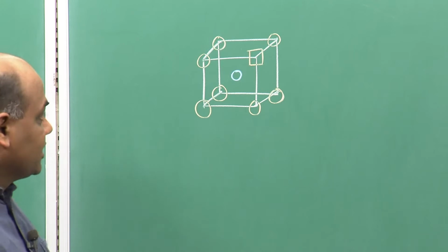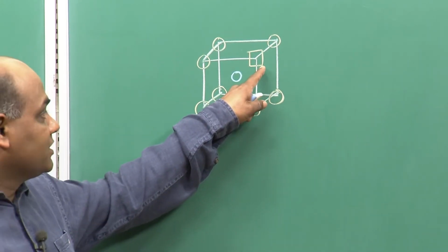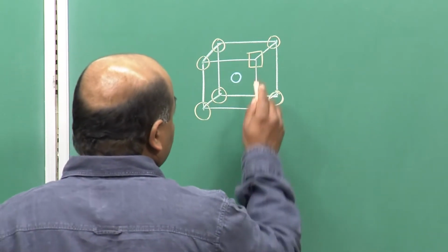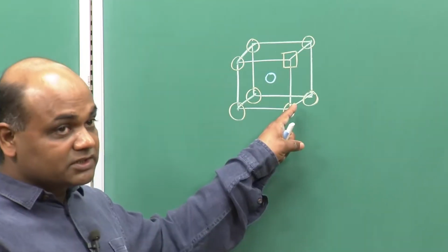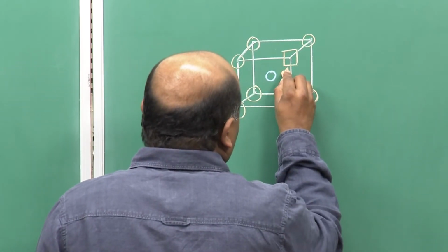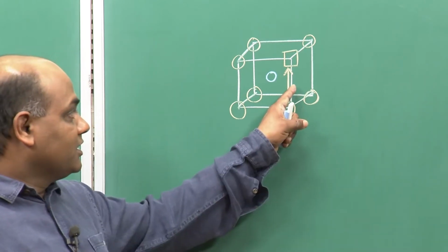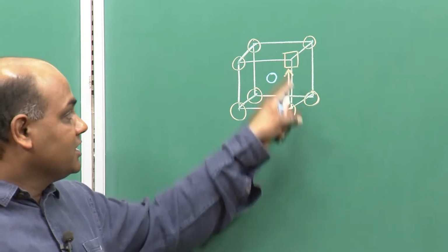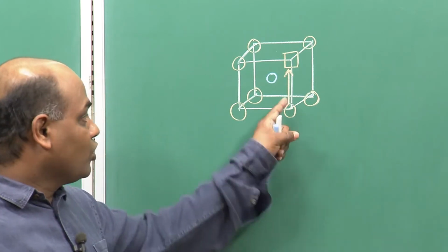In a B2 structure, if there is a vacancy on B sublattice denoted by the square here, another B atom can jump onto that vacancy, and the B atom is located on the next nearest neighbor site of this vacancy. So, this is the next nearest neighbor jump, and you can see exchanging with the vacancy on the next nearest neighbor site is not causing any disorder, that is, no wrong bonds are formed.